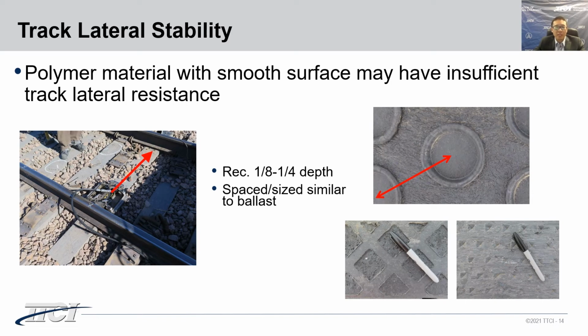Three types of composite ties with different patterns of surface texture were selected for a single tie push test. Two types of ties had a texturing approximately 1/4 inch in depth. Another type had a texturing around 1/8 inch in depth. The spacing of the surface patterns is similar to the size of a nominal ballast particle.